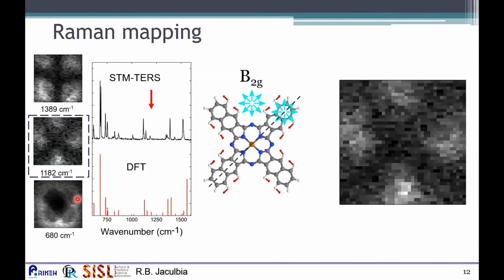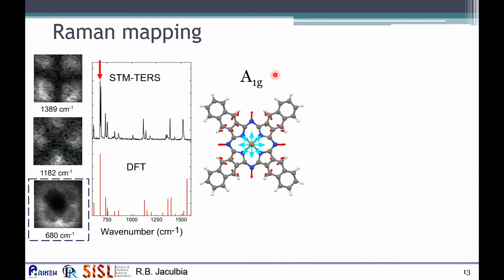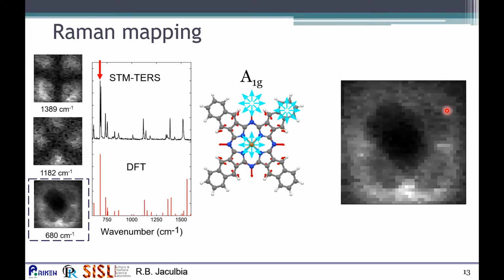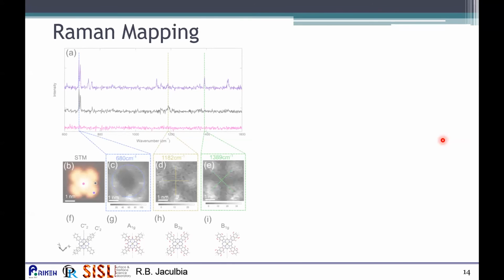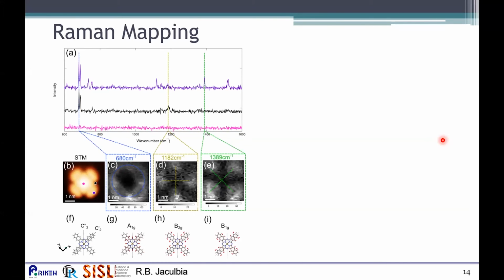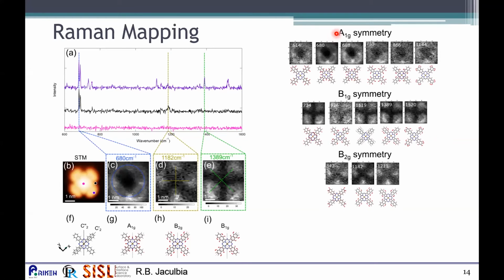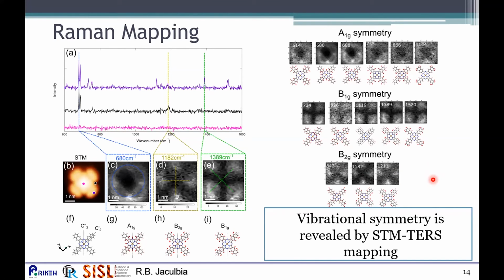On the other hand, the 680 mode is an A1G mode. It's basically symmetric in all directions, so it's basically enhanced everywhere. So when we check all our Raman maps, we can classify them according to the symmetry. A1G is the circular, B1G is the cross, and B2G is the plus. So our observations suggest that the vibrational symmetry can be revealed by STM TERS mapping under direct molecular resonance conditions.